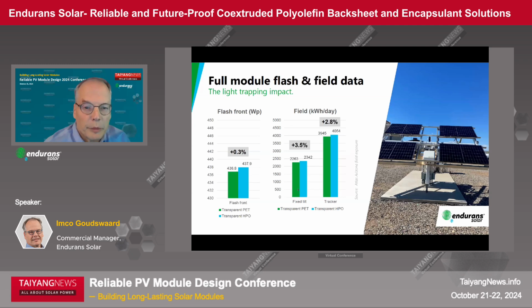And then this is, let's say, the proof of the pudding on the light trapping effect. On the left bar, you see the flash test result of a full-size TOPCon module, where, due to the somewhat higher reflection all over the surface, we get a slightly higher output, but that's minimal. And the big difference is when you put these modules in the field. On the right side, you see a picture. These have been positioned in Arizona on a tracker, using the tracking system, but also fixed tilt. And on the right graph, you can see that the additional power output is increased by roughly 3%, depending on whether you use a fixed tilt or a tracker. So that's the main advantage of the light trapping concept. Next slide.